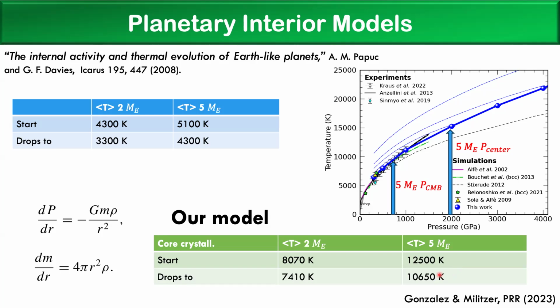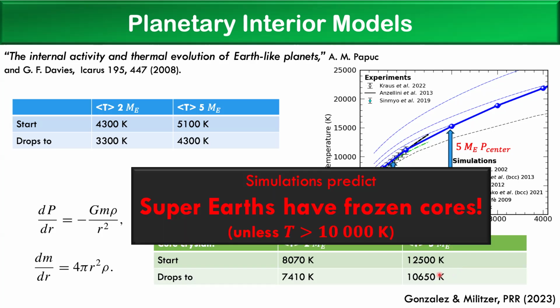So that would eventually mean that these simulations predict that super-Earths might have frozen cores entirely, unless you're able to maintain a temperature that's beyond 10,000 Kelvin. Now, is this temperature too much or too little? Well, that depends on how much energy was delivered on accretion and whether models are compatible with such a high temperature in the beginning.